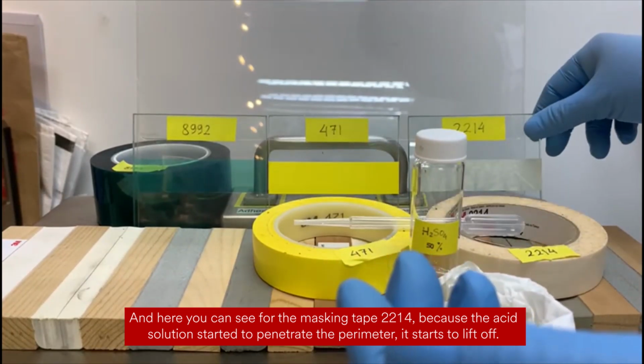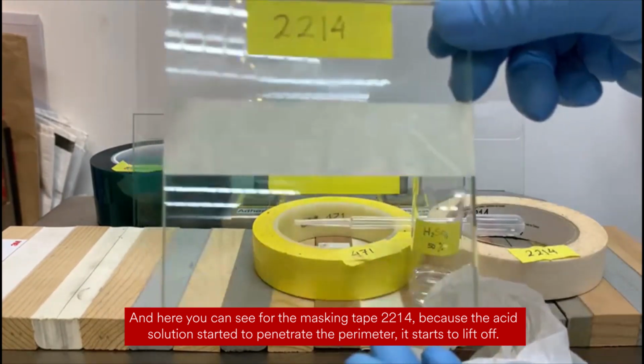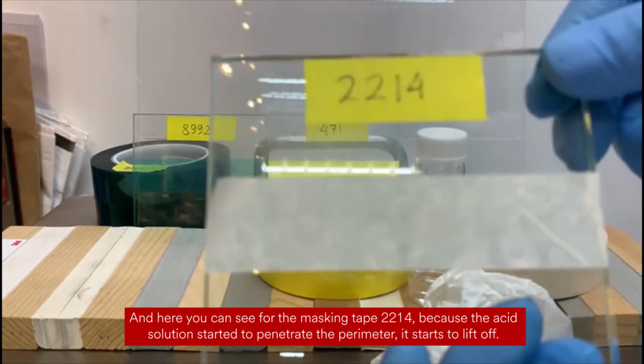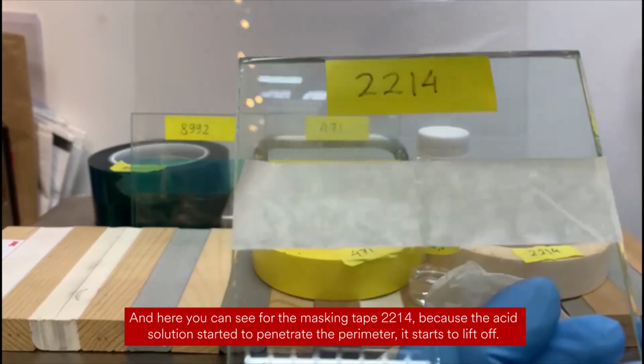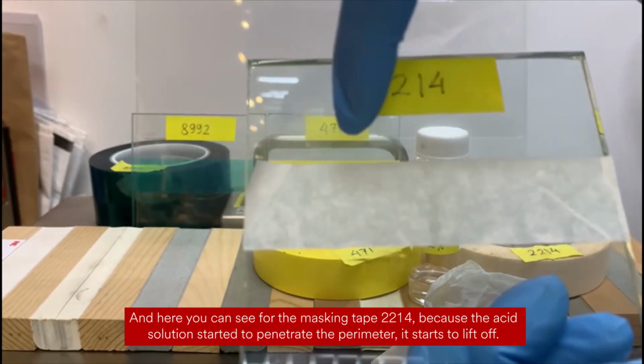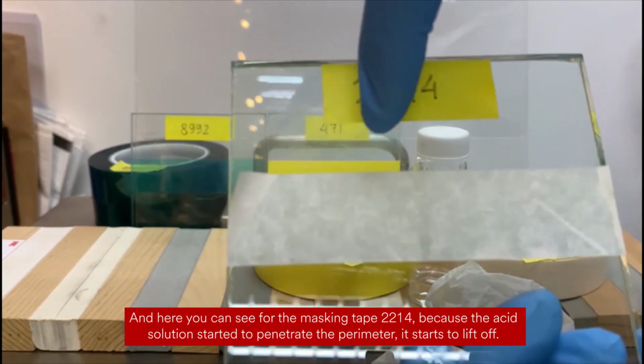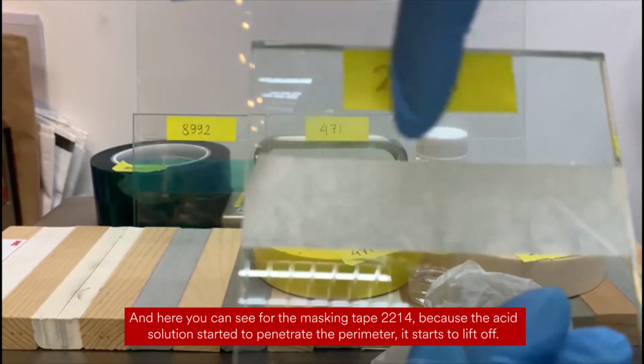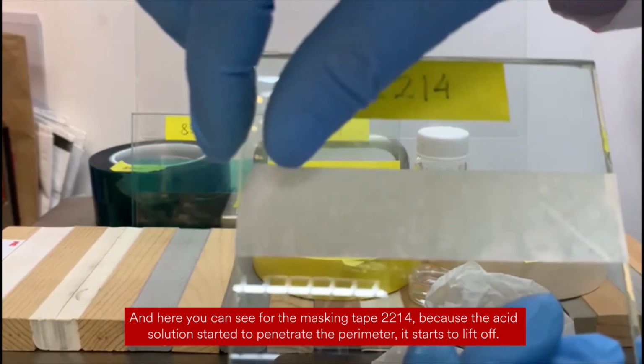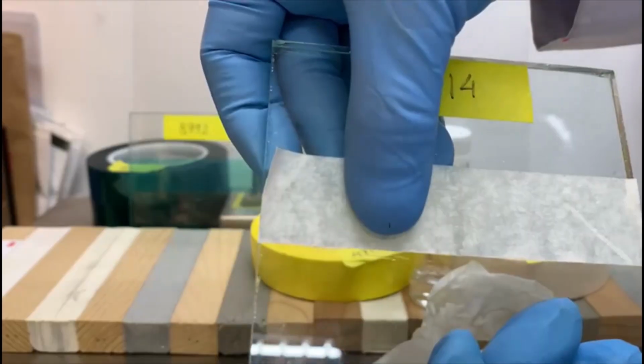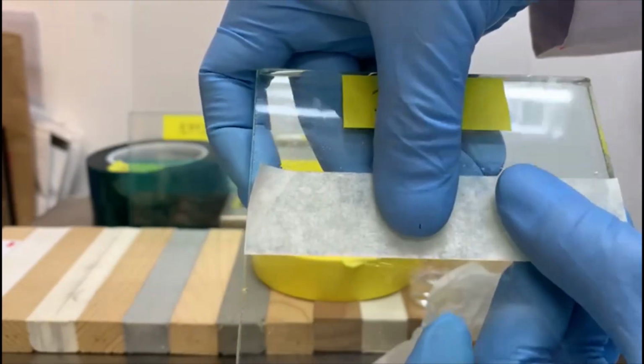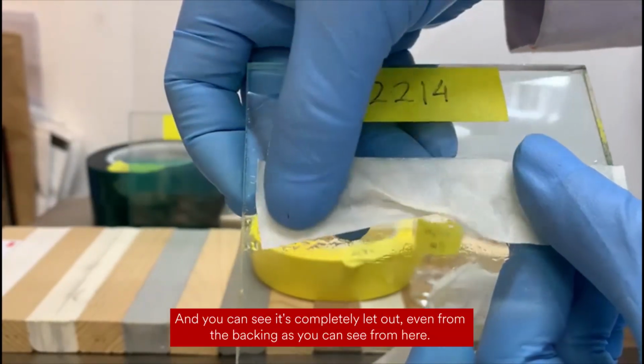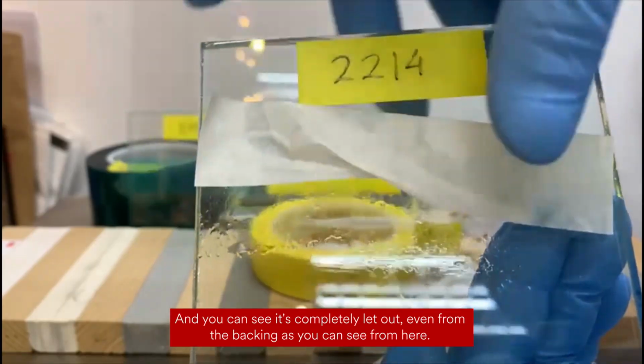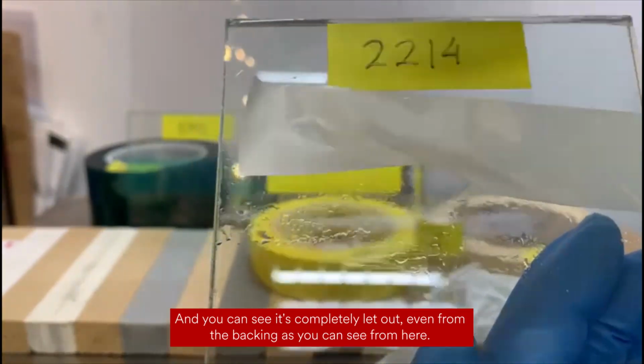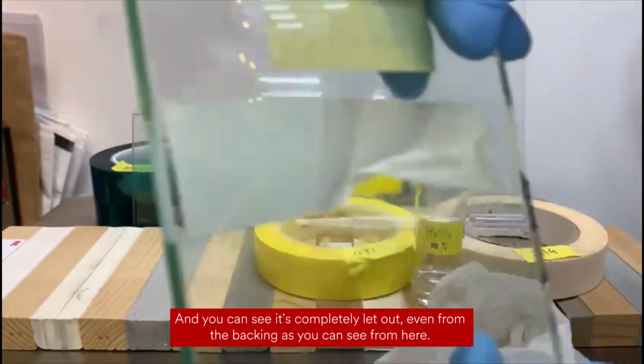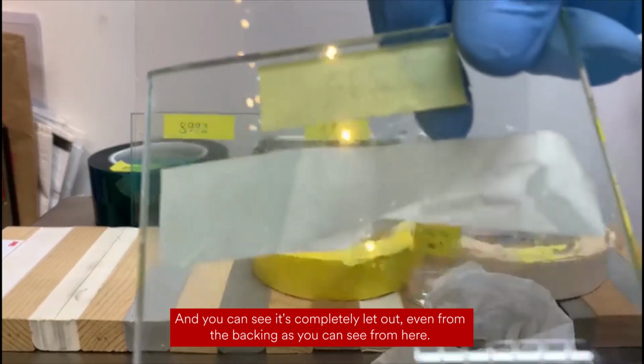And here, you can see masking tape 2214. Because the acid solution started to penetrate through the perimeter, it started to lift off, and you could see it's completely wet out from the backing. You can see from here.